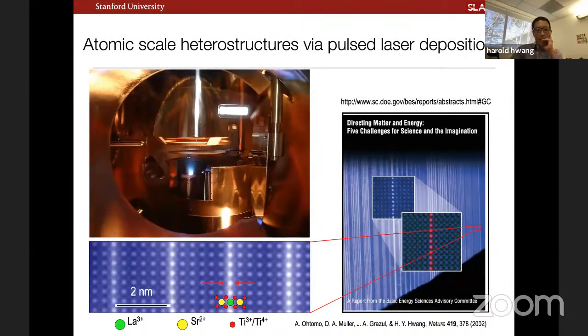So to give you just some eye candy of how this looks, this is a picture inside one of our chambers. We're using pulsed laser deposition, and for the last two decades or so, we've been working a lot on making artificial heterostructures where we try to get down to fairly precise atomic control. So this is a fairly elaborate and somewhat expensive technique. As I'll discuss later, the nickelates have now been stabilized by a number of groups, using pulsed laser deposition but also molecular beam epitaxy and so on. So this is how we're growing the perovskite precursor phase.